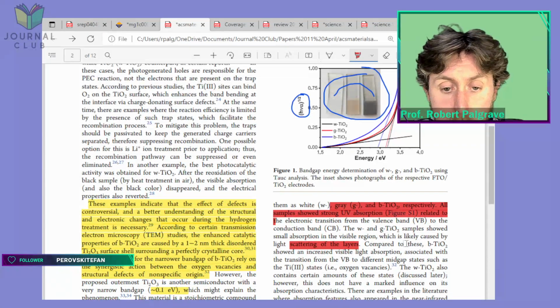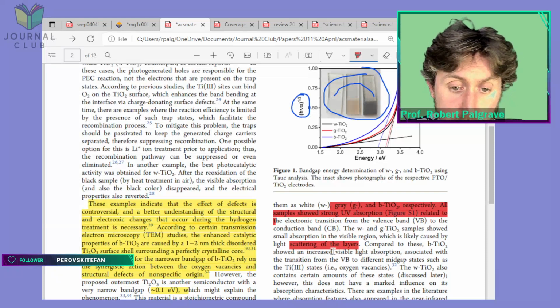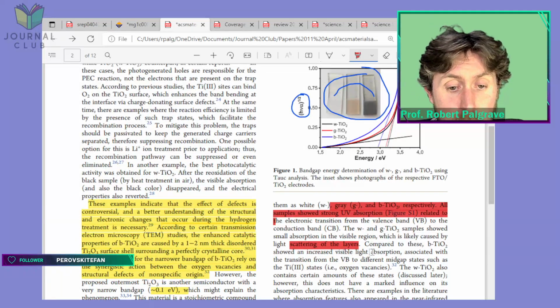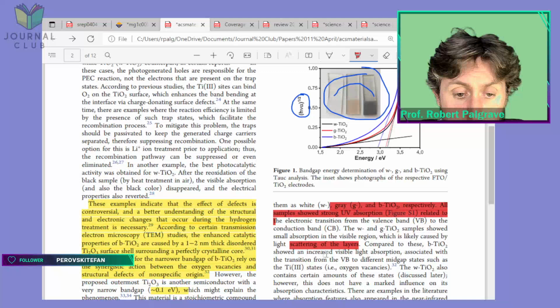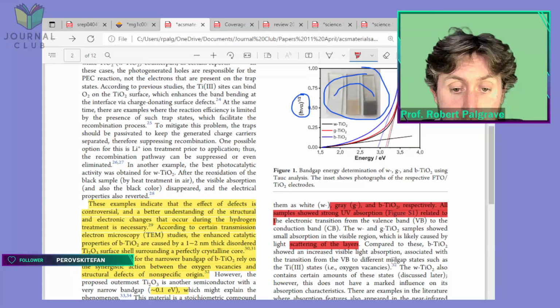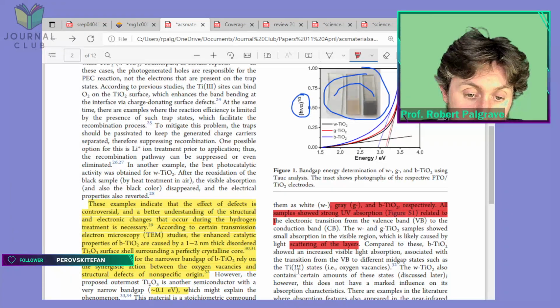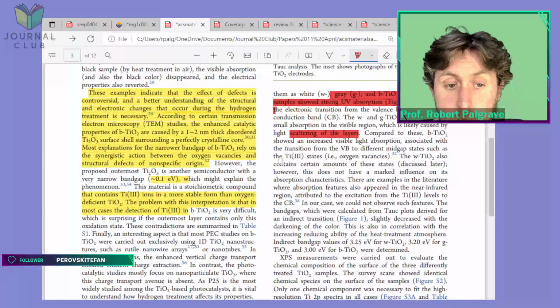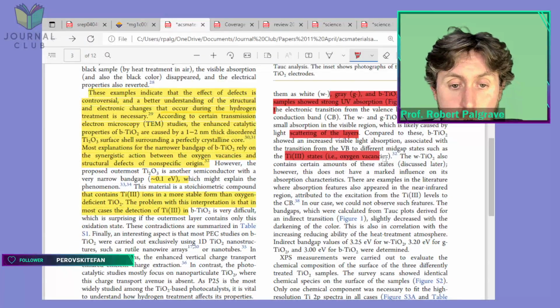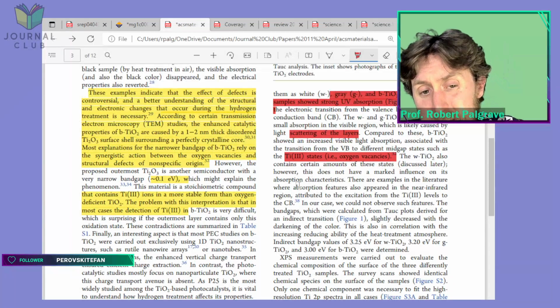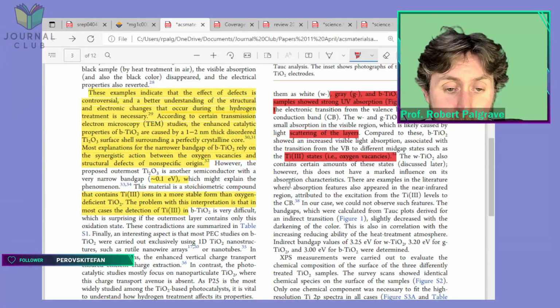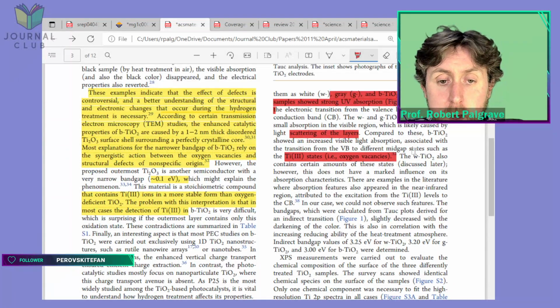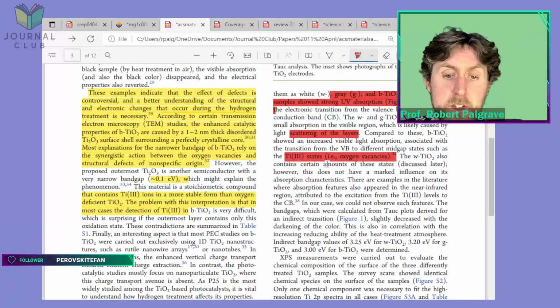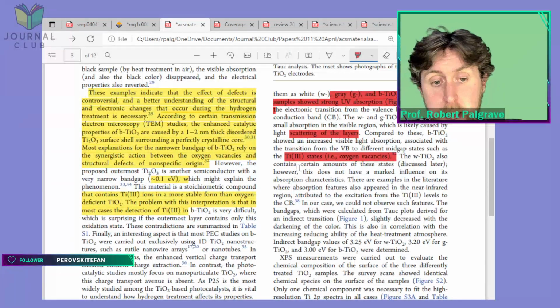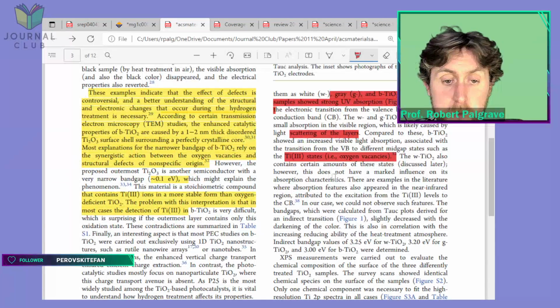Compared to the black TiO2, it showed an increased visible light absorption, only a little bit more, associated with the transition from the valence band to different mid-gap states, such as Ti3+ state, i.e. oxygen vacancies. Well, identification of Ti3+ with oxygen vacancies, it's not literally the same thing, but I kind of get what they mean. The white TiO2 also contains certain amounts of these states, discussed later. However, this does not seem to have a marked influence on the absorption characteristics of the white TiO2, maybe.